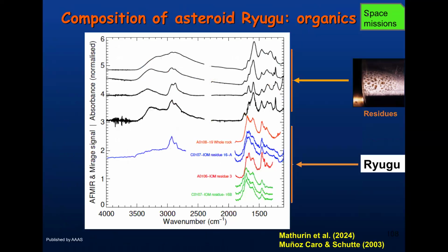Very recently, a few months ago, they also did infrared spectroscopy of Hayabusa 2 samples from asteroid Ryugu, and they compared it to our residues. So you can see here, the 4 in black are our residue spectra, and these are Hayabusa spectra. So you can see very clear similarities between both. So the conclusion is that, at least spectroscopically, the Hayabusa samples, they are compatible with the residues we make by ice irradiation.